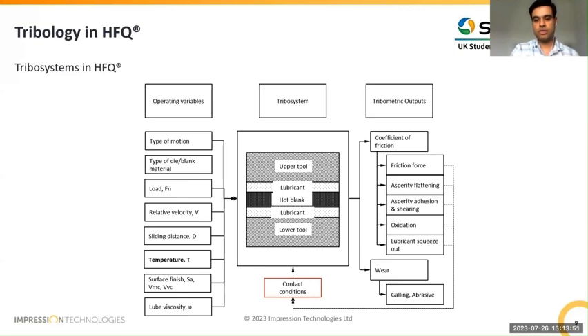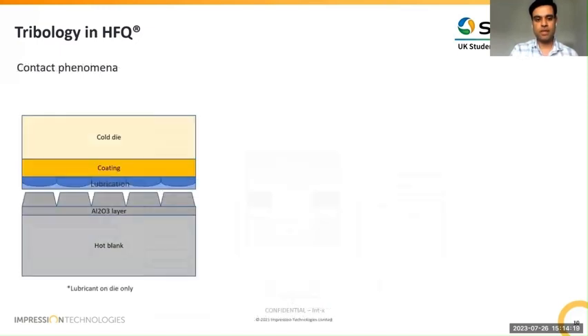So what is different to other tribology domains here is that the contact is non-recurring, that the blank and the tool only come in contact with each other once. Then there is an area contact rather than line or point contact. And the contact pressures that we experience are in megapascals. So let's say up to 50 megapascals on average, rather than in gigapascals. So the contact is very different.